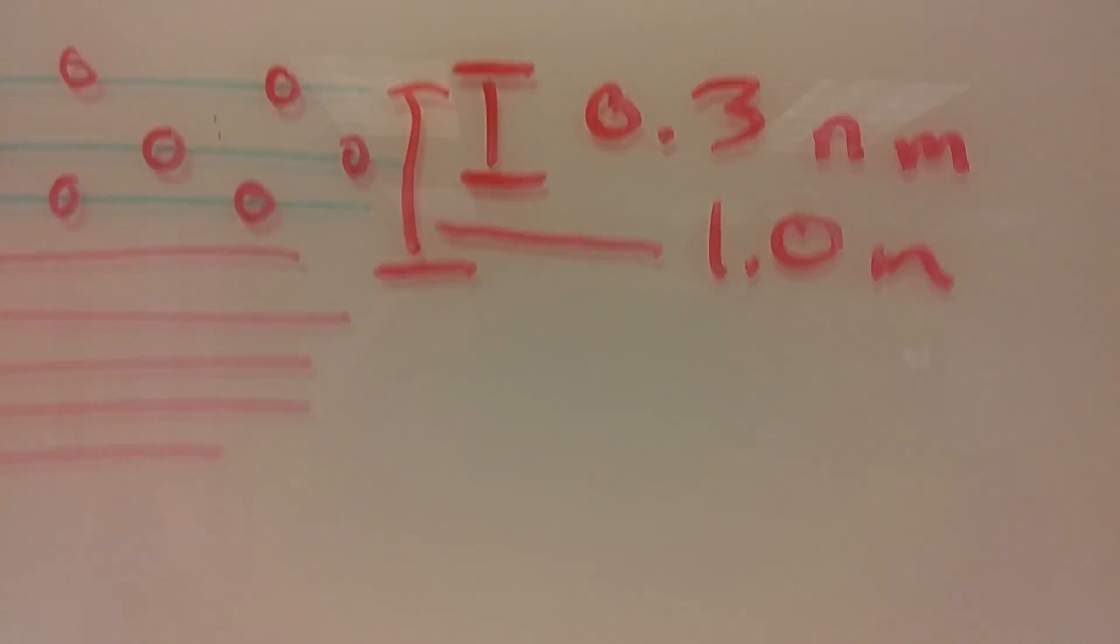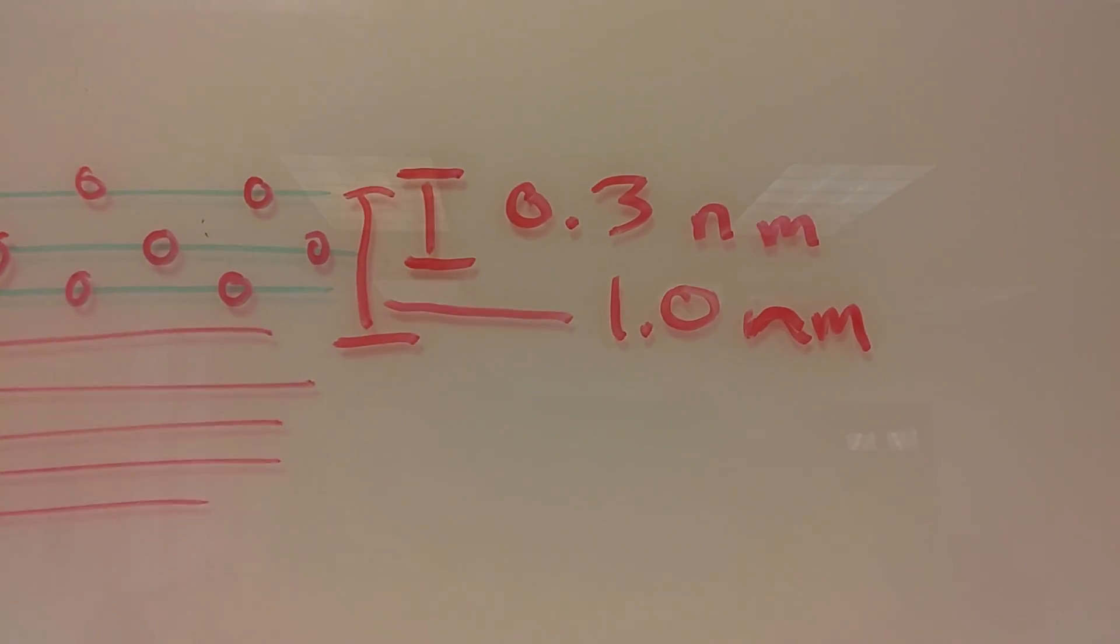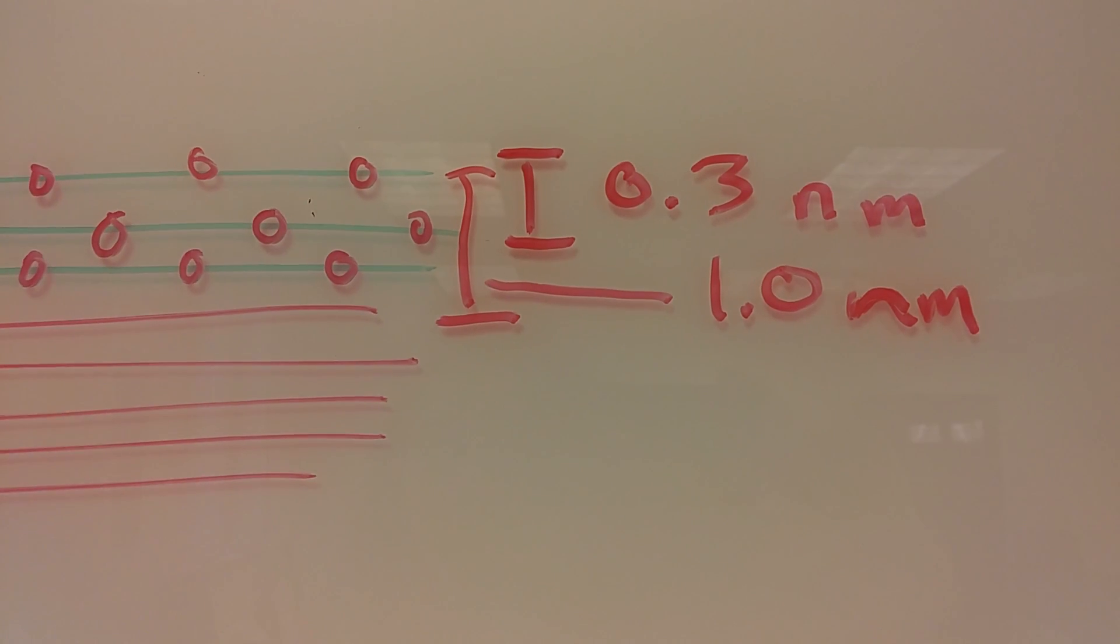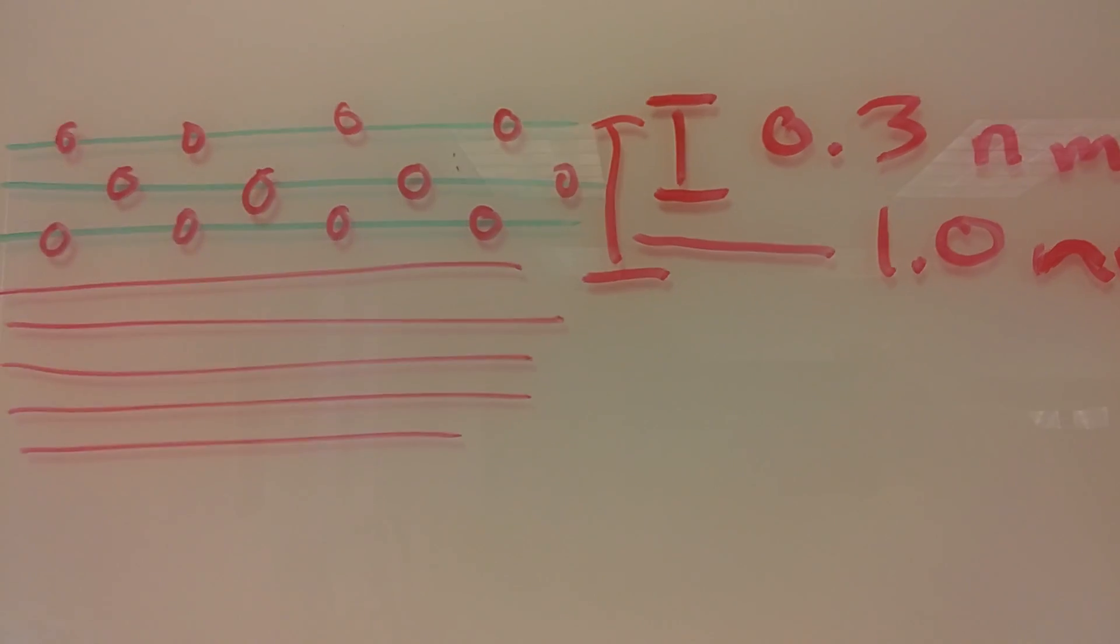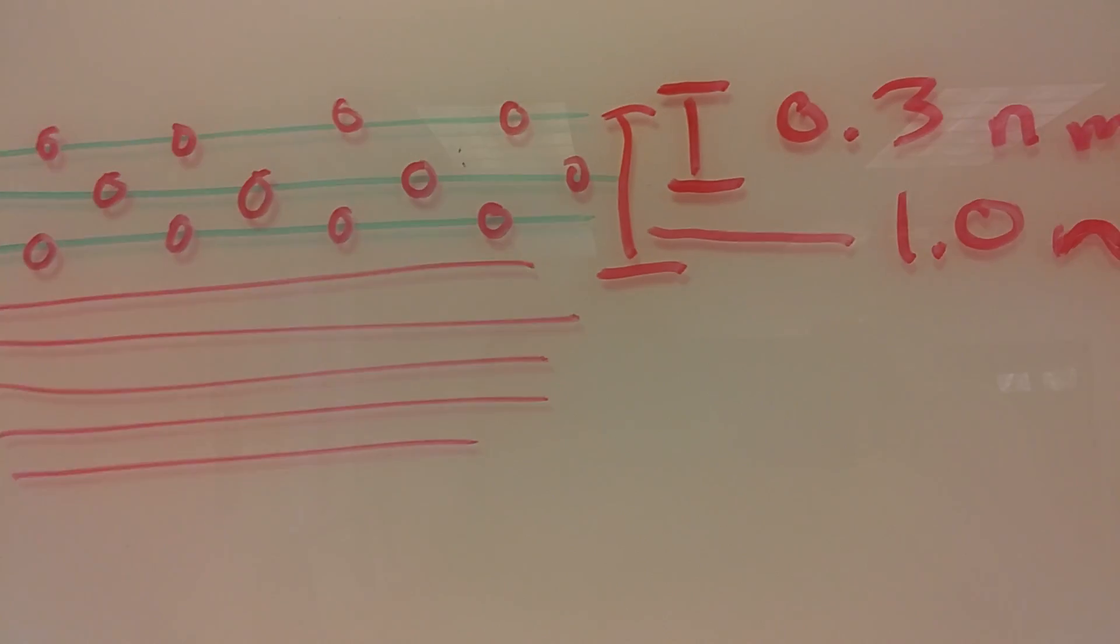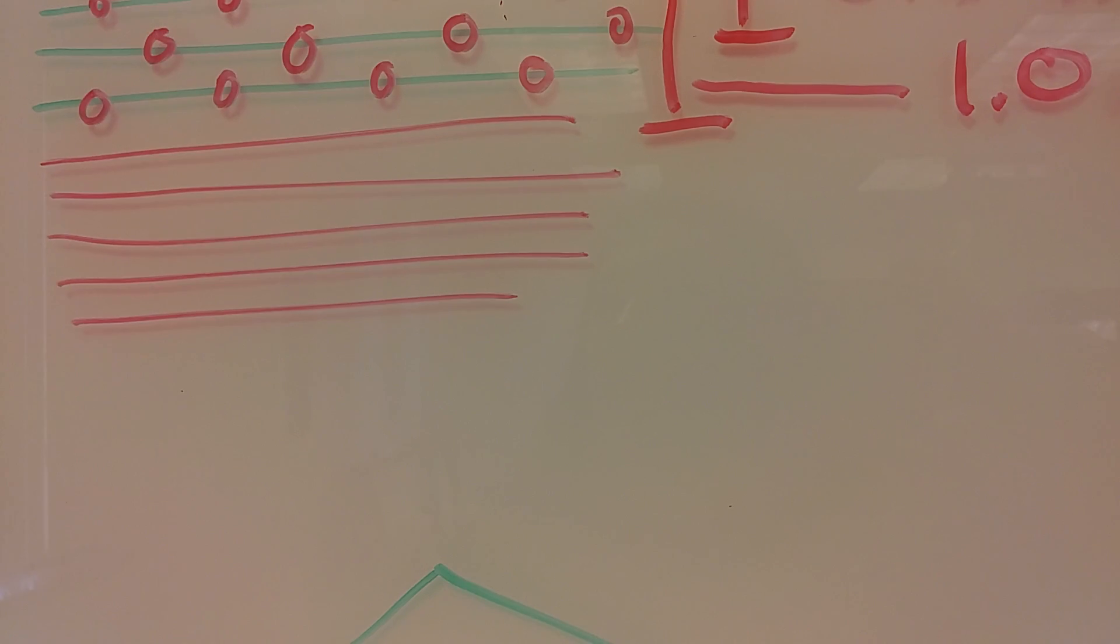This is with even CVD. You're going to have a range of 0.3 to one nanometer. That's it. If it's not 0.3 to 1 nanometer, you're above one to three layers and you're going to see significant losses. You can go up to six, maybe even eight layers, and you'll have a very close product, you'll have something similar.